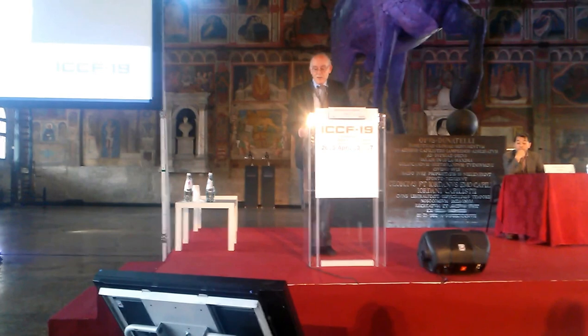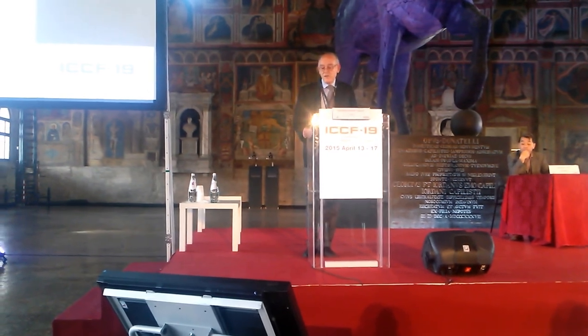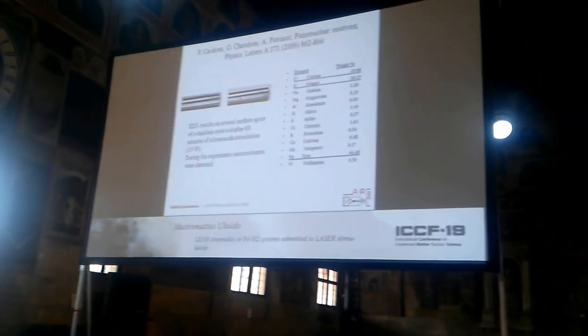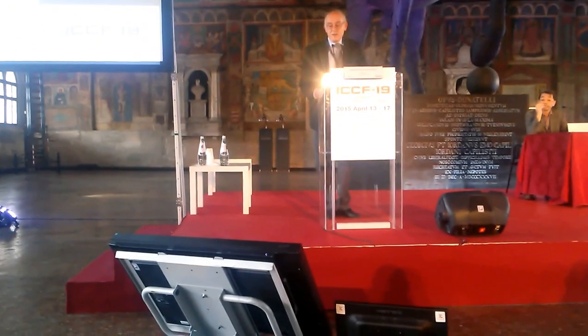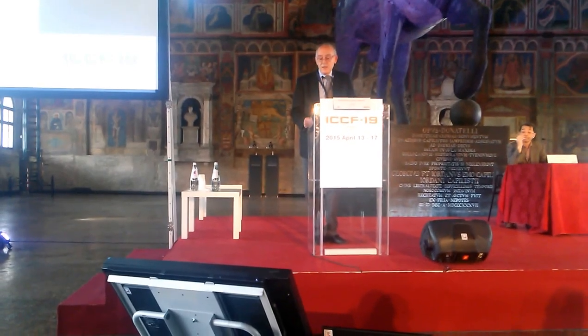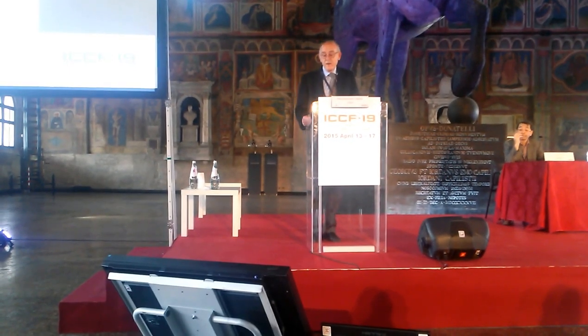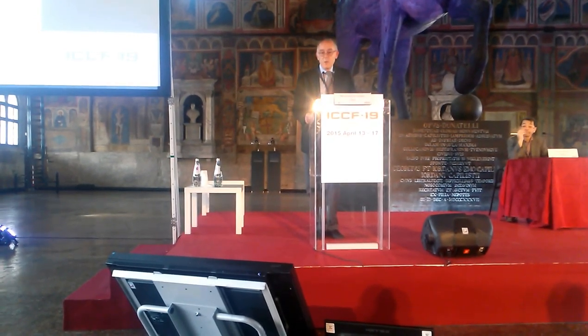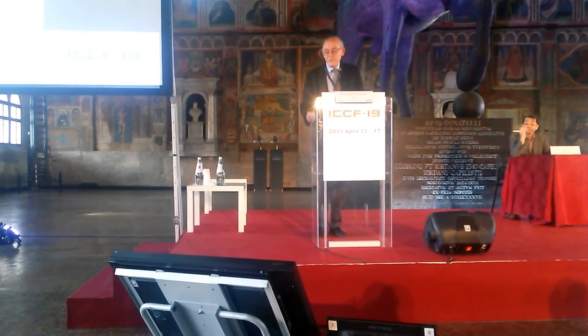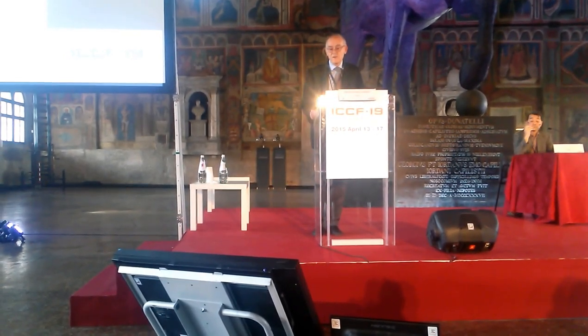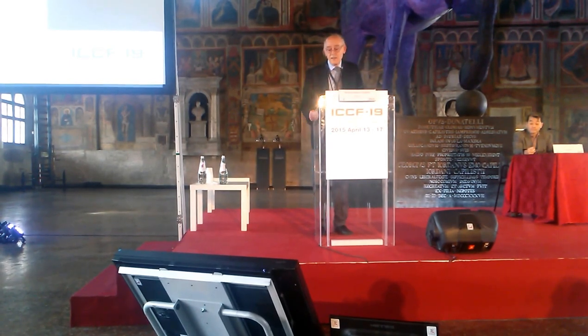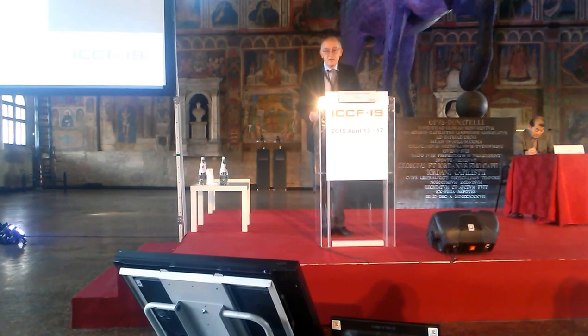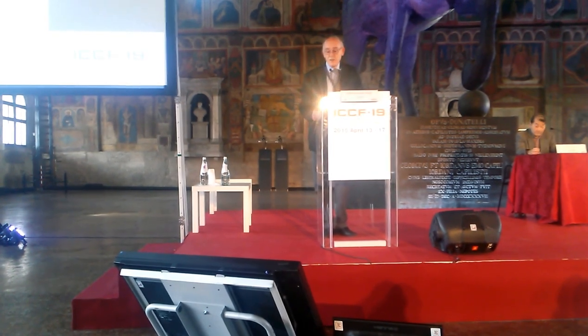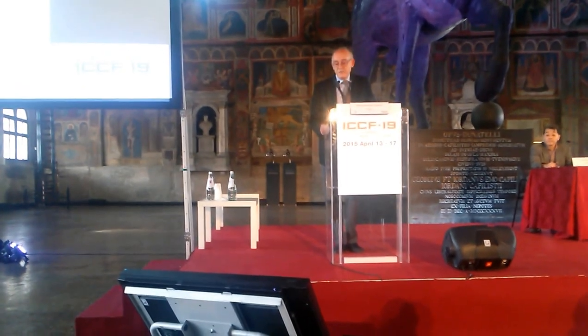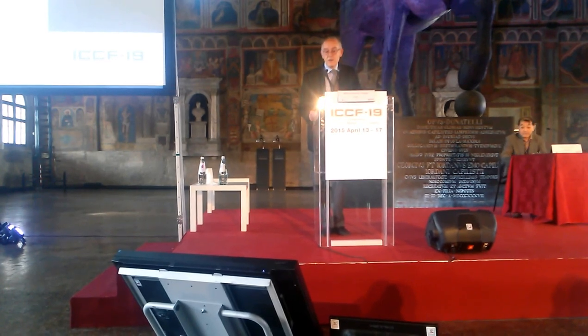This is a particular experiment, I don't know if you are aware of that, using a different kind of stimulation in the reactor. They were using ultrasounds, as is explained in the notes. They had just 1 hour of ultrasounds, 90 watts in water, in very clean water, and the material submitted to this stimulation was stainless steel. You can see pictures of the material before and after the stimulation, and many hot spots appeared on the surface.